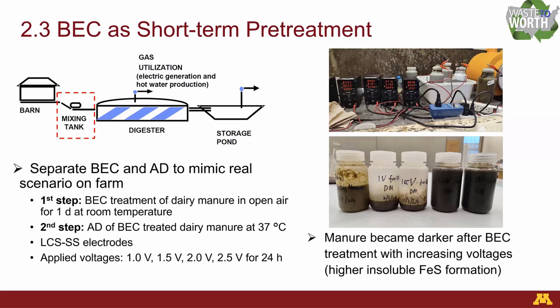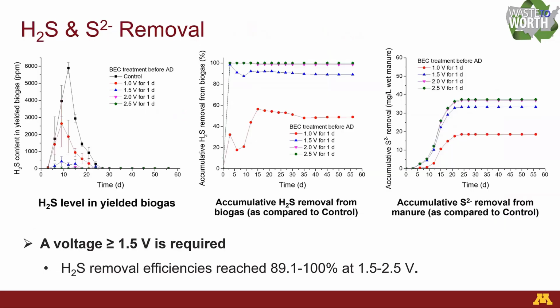So we can see the manure became darker with the increase of the voltage here because of the formation of more black insoluble ferrous sulfide compounds. And this is the hydrogen sulfide and aqueous sulfide removal. So we can see all of the groups showed certain effectiveness in removing sulfide, but a low voltage of 1 volt is not efficient enough to remove all of it, while a voltage of over 1.5 can remove almost 90% of the sulfide from the biogas.